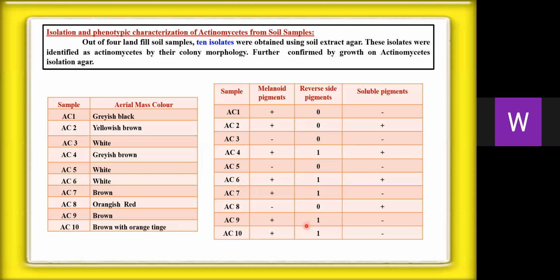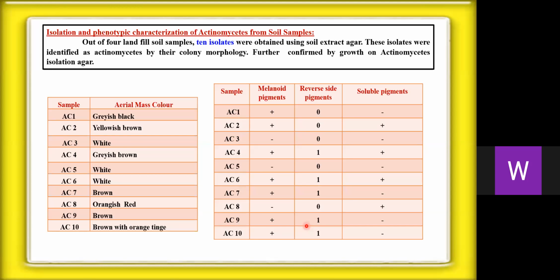These isolates were identified as actinomyces by their colony morphology, aerial mass color, melanoid pigment, reverse pigment, and soluble pigment. Further confirmation was by the growth on actinomyces isolation agar. These actinomyces strains show a varied range of aerial mass color, from grayish black and yellowish brown to orangish red. Most of the actinomyces strains show melanoid pigment production, whereas few strains showed reverse side and soluble pigments.